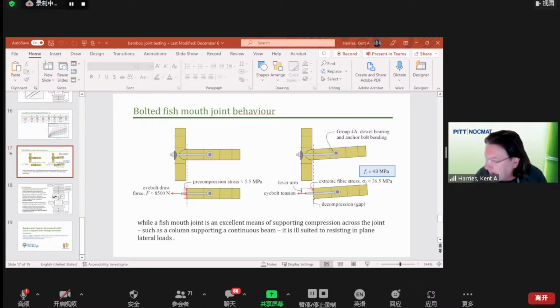How we determined the pre-compression force was actually by trial and error. We wanted the largest pre-compression that we could get, which would maximize the moment capacity without crushing the column, in which case we did a number of trials to make sure that we were in the right ballpark. And you can see the force that we ended up with. That's an average force. It did vary a reasonable amount, about 8,500 newtons, which was fairly significant. And we, of course, ensured that a node was nearby, which helps us out. We are presently running tests that look at what level of eyebolt force we could run based on, for instance, the size of the fender washer and what have you.